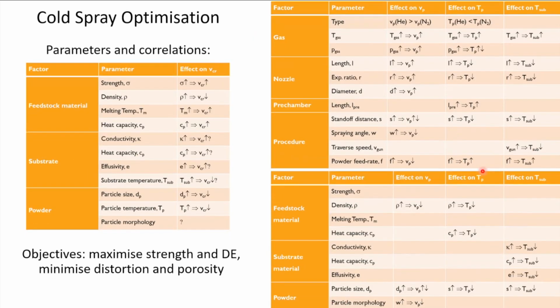Now, with the practical application, you do a lot of experiments on the different conditions of the strain, and you end up with a lot of correlations and a lot of parameters. So this is a concise list of correlations and the parameters and factors that are relevant. If you want to find the sweet spot by performing experiments with all these factors as variables, you will not succeed, because for each variable you need to increment that variable within a range and then end up performing millions of experiments. So that's not feasible. That's also a practical problem.